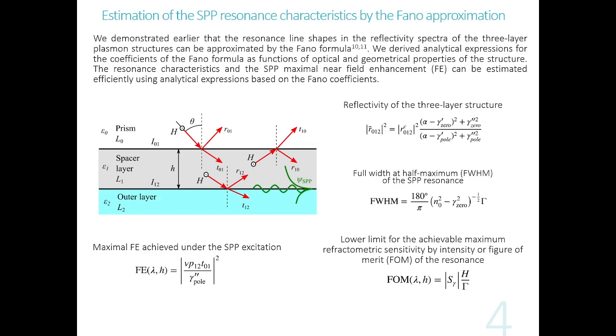Our goal for this research is to demonstrate the resonance characteristics for a planar structure, which allows surface plasmons to propagate. The way of estimation of the resonance characteristics is based on the Fano approximation formalism, which was discussed in detail and demonstrated in previous papers of some of the co-authors of the present research. It's based on approximation of the attenuated total reflectance spectrum of these structures by the Fano formula. This method allows us to select some important characteristics such as full width at half maximum, field enhancement, or estimation of the sensitivity by intensity, and to estimate all of these characteristics directly using the optical characteristics of the films of the structure.